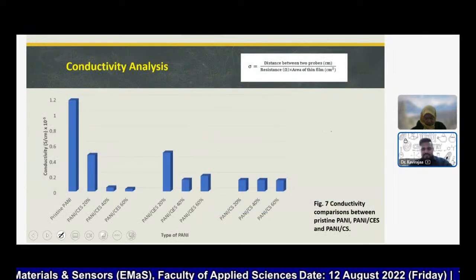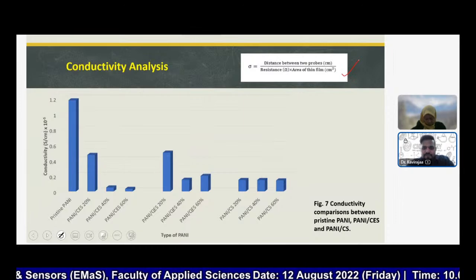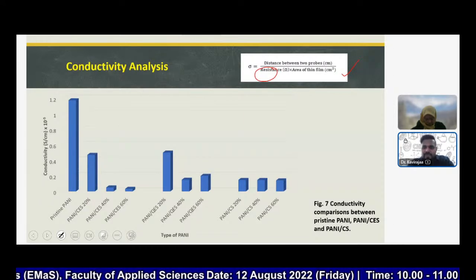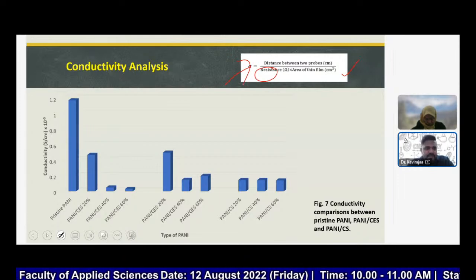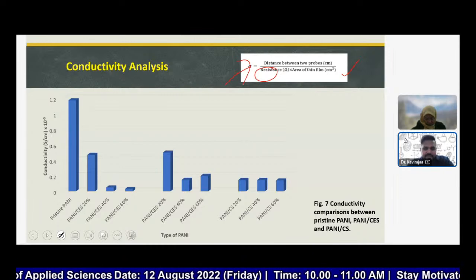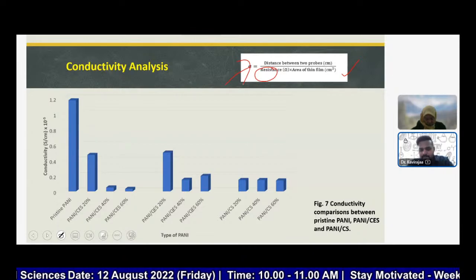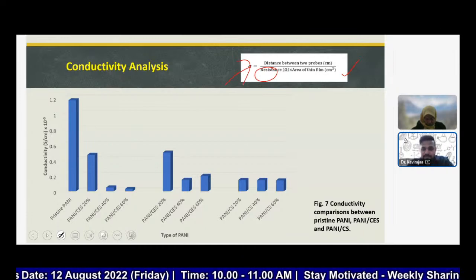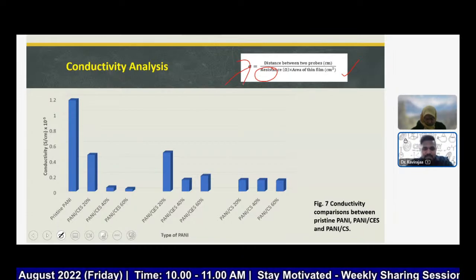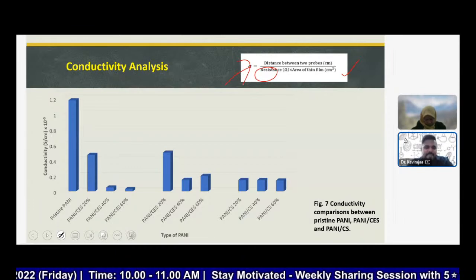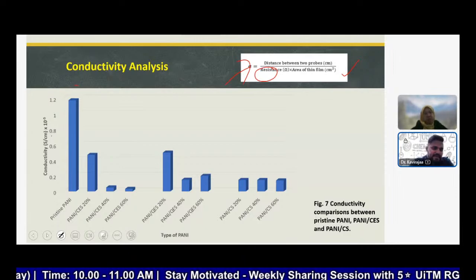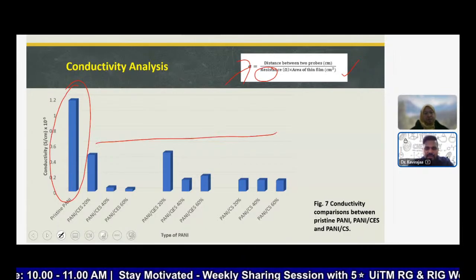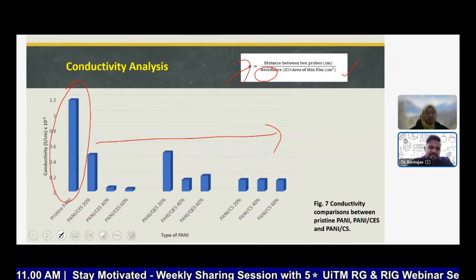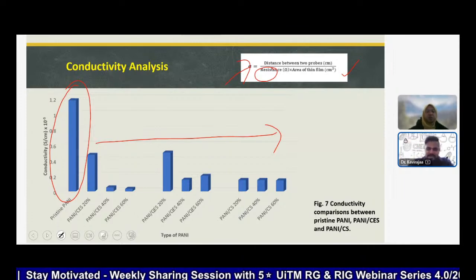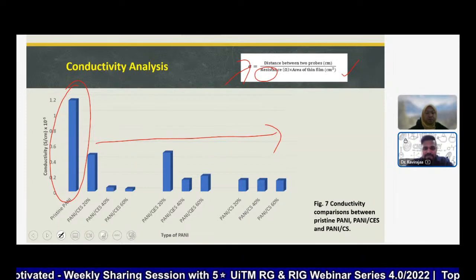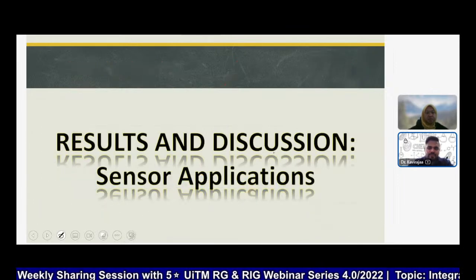Okay, so this is the conductivity analysis. This is a formula that we normally use. We will calculate the resistance, and then we will use this formula to calculate back the conductivity. So here, this is the one that I told you. This is not directly related to the absorbance, but we can do some kind of absorbance ratio study, where it can be related. Okay, so it's a typical scenario where pristine PANI normally will have a higher conductivity compared to any of the other composites, because the fillers that we are adding in are non-conductive. So definitely it's going to suppress the conductivity, but it doesn't compromise the gas sensing measurement. So that's what we're going to see now.